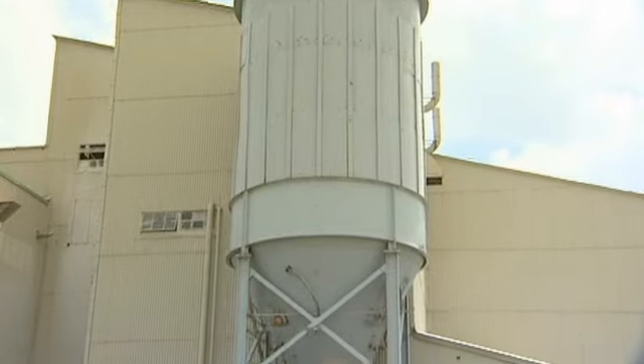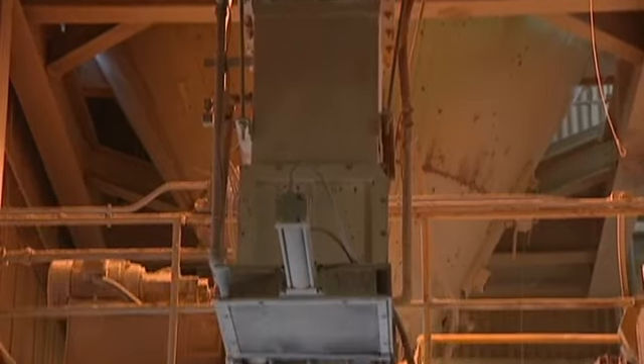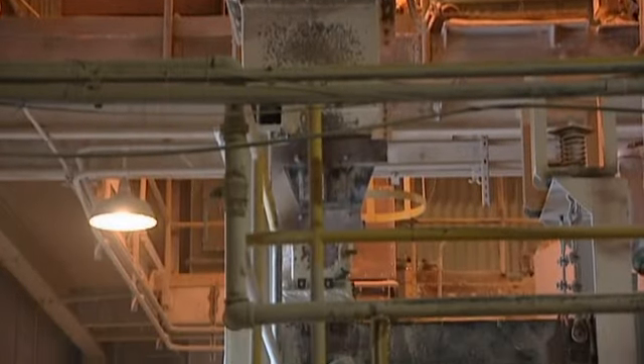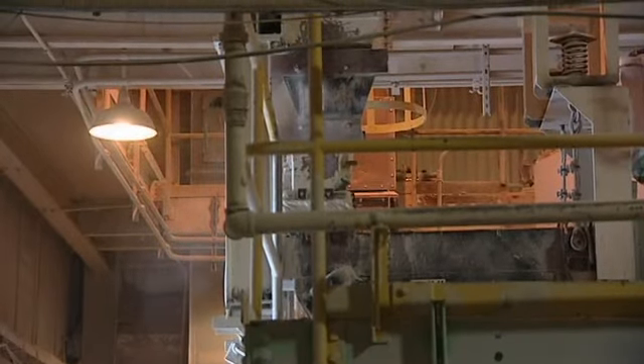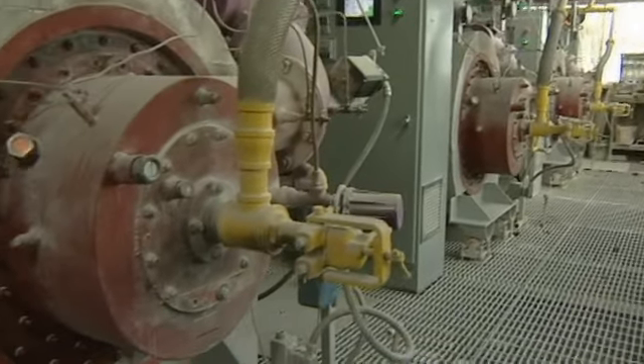Okay, so the object here is to get it as dry as possible then? Yes, it is. The rock dryer is taking away the free water, which is rain, snow, sleet, and we're left with gypsum. Bring it into the plant here, and there we're going to grind it, and we're going to calcine it. That chemically combined water, we're going to take out 75% of it in the mill. From there, it's called stucco.